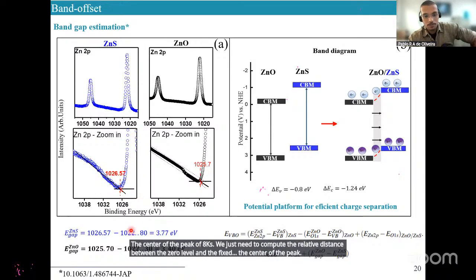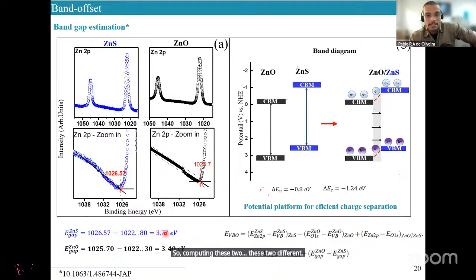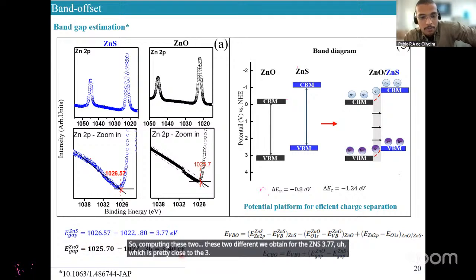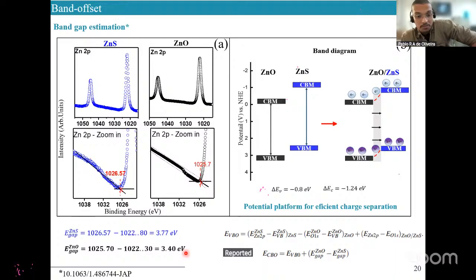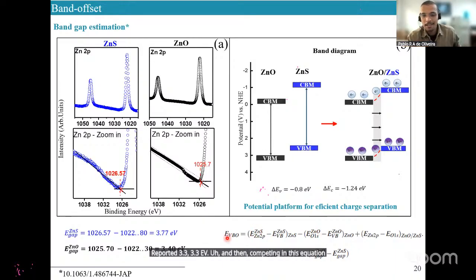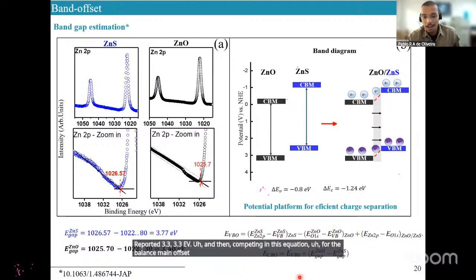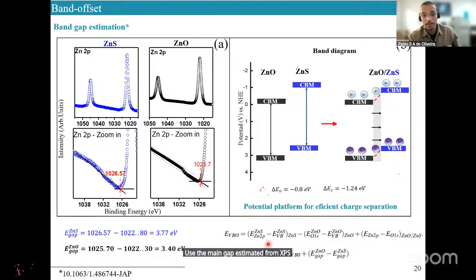Computing these two differences, we obtain 3.77 eV for the ZnS, which is pretty close to the reported 3.6, and 3.4 for ZnO, which is close to the reported 3.3, 3.2 eV. And then computing this equation for the valence band offset, you can now use the band gap estimated from XPS to compute the conduction band offset. Overall, these parameters and values are reported in panel B.